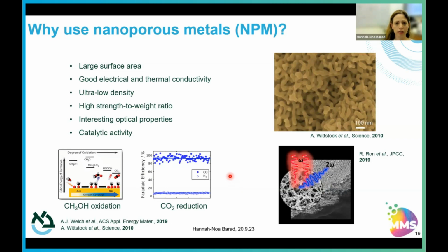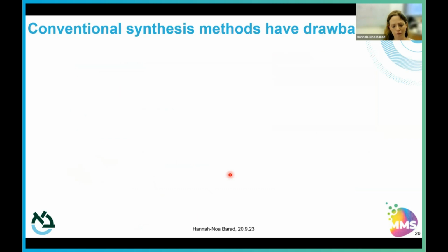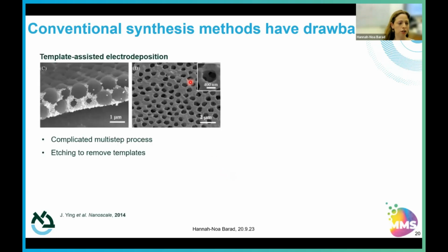And what we were trying to do is see if we could maybe use glancing angle deposition to make a direct method to actually be able to form these nanoporous metal structures without having to use all of the components that are usually used, which the conventional synthesis methods have really a lot of drawbacks, I have to say. So a lot of times people use these template-assisted electrodeposition methods, which are fine, but then you end up having to etch to remove the templates, which are, of course, a lot of times corrosive environments.